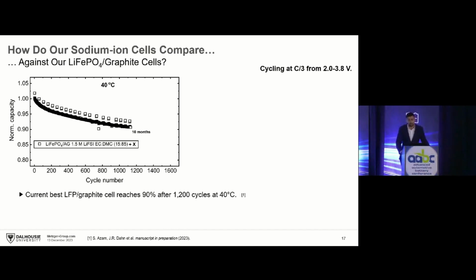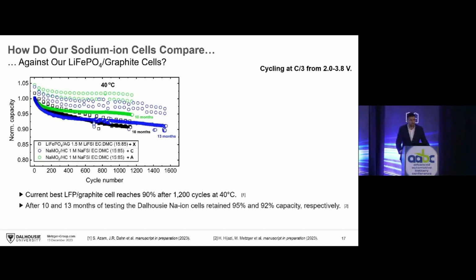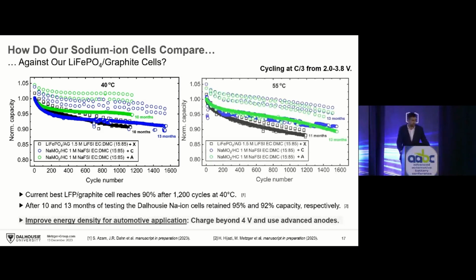The cell cycling for about 10 months at 40 degrees Celsius reaches about 90% capacity retention after 1,200 cycles at 40 degrees C. And our sodium-ion cells, when they're charging to 3.8 volts with advanced electrolytes, they can have better cycle life than LFP. So these cells are cycling for 10 months and 13 months respectively, and they retain 95% or 92% of their capacity. What happens at higher temperatures, 55 degrees C? There, the sodium-ion cells are even better. So they retain their capacity better than LFP graphite cells at elevated temperature.